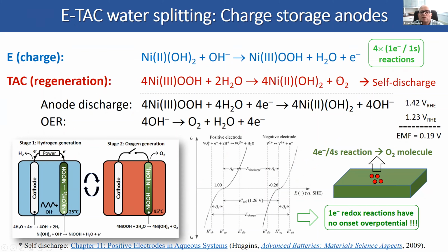evolve the oxygen molecule. Essentially, although this is a chemical reaction, it is like any other kind of corrosion reaction, it comprises a complementary anodic and cathodic reaction, where the anodic reaction would be exactly the opposite of the charging reaction. And you also have the OER. So I do not say that we replace the OER, but we do the OER in a different pathway that goes through 4 sites instead of 1 site. And that is what enables us to reduce the large overpotential loss that you have for normal electrolysis.